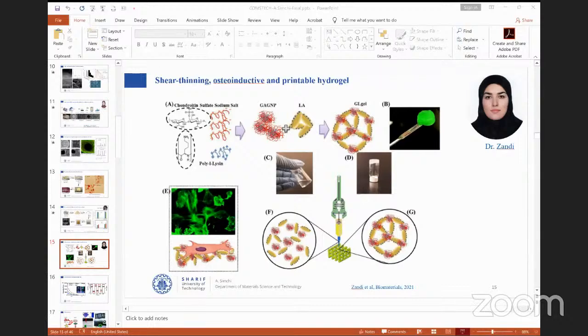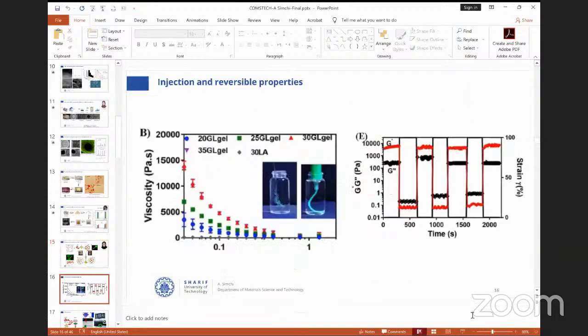And this brings a significant opportunity to manufacture scaffolds, which is printable. And the most important thing from this work, which is published in Biomaterials, is that we show the gelation is reversible. When we prepare the material as a gel, it's a solid material. When we insert a force, a shear, on that, it turns to a liquid. And this process, as you see on the right-hand side, is reversible. So this can change from gel to liquid, gel to liquid.